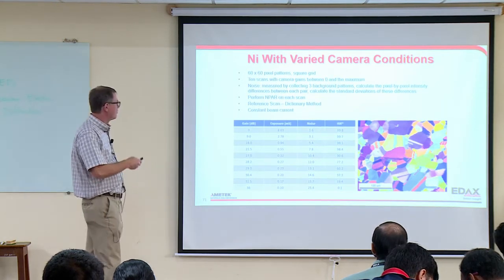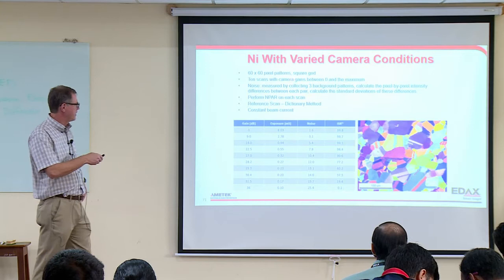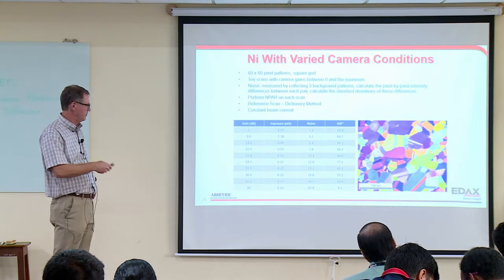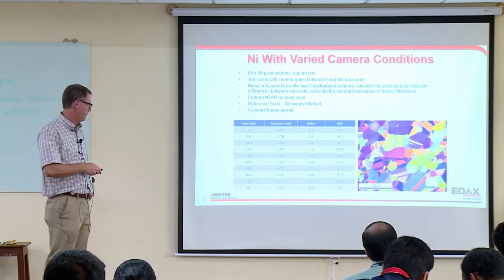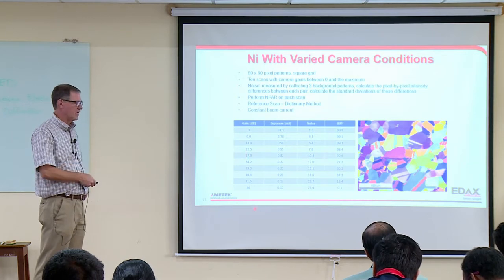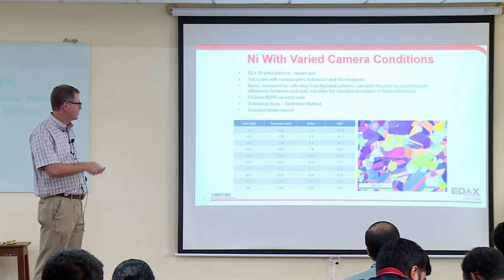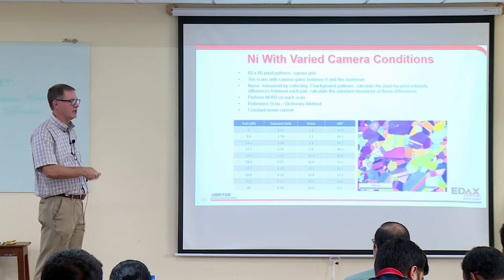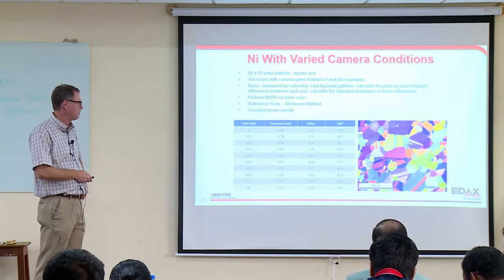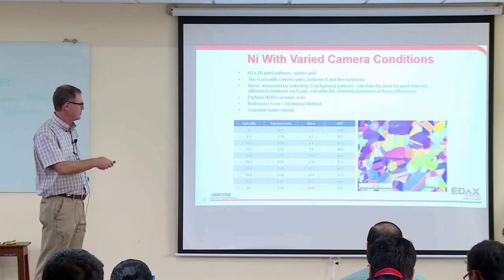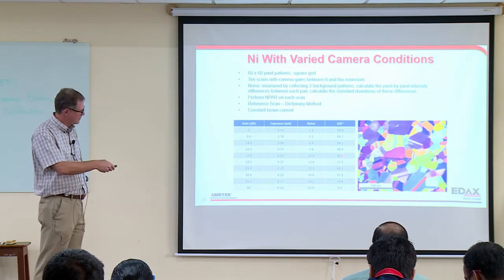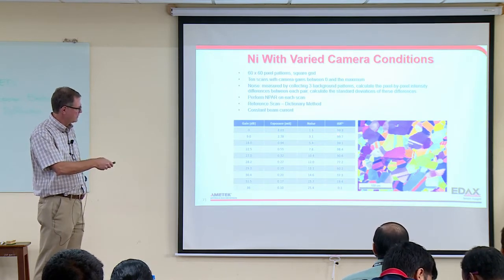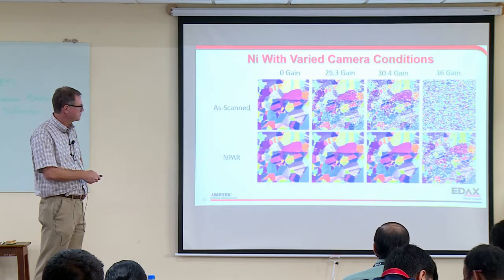So we've done the same thing where we've collected a bunch of patterns, but now we do the same scan of the same area 10 times. But we do it with increasing gain. So we're increasing the noise in our patterns. We also increased contamination as we went, so we're getting more noise that way too. But you can see we're getting more and more noise, and our indexing success rates are dropping, and they stay high and then drop pretty rapidly.